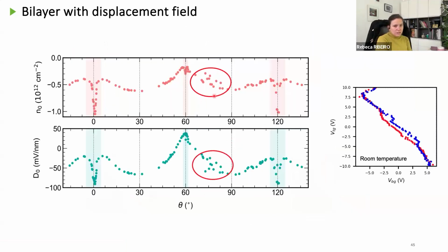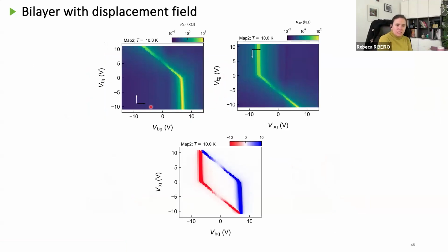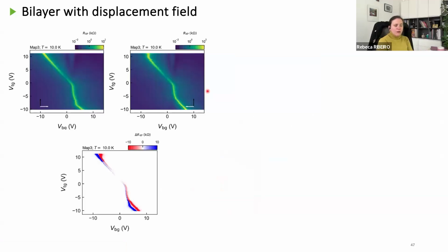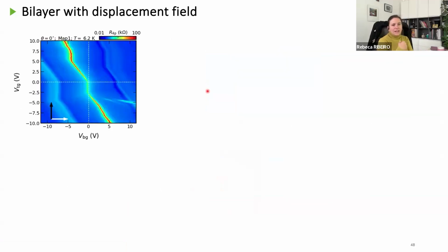However, you can see here that we are not in the aligned position. We are close to a misaligned position, so we should not have any moiré superlattice, and we don't see any moiré satellite peaks. So it means that we are not necessarily aligned. However, we also observe this behavior for an aligned device, a different device. You can see the satellite peaks.